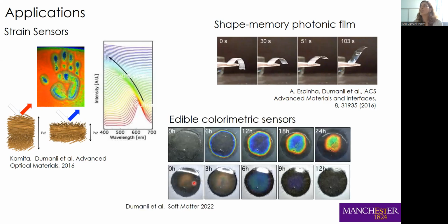And the edible colorimetric sensors we developed, we again worked with the HPC for that and encapsulated it into shellac. The shellac is a semi-permeable polymer, which allowed us to time the evaporation rate of the HPC liquid crystalline form, and you can time that by tuning the shellac layer that covers the HPC.